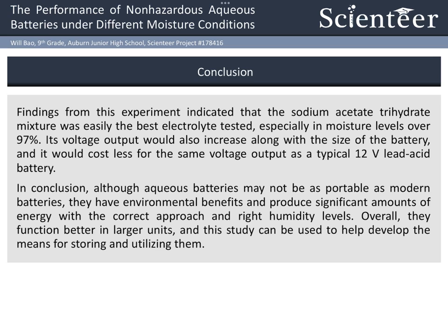Findings from this experiment indicated that the sodium acetate trihydrate with distilled water mixture was easily the best electrolyte tested, especially in moisture levels over 97%. Its voltage output also increased along with the size of the battery, and it would cost less for the same voltage output as a typical 12-volt lead-acid battery.